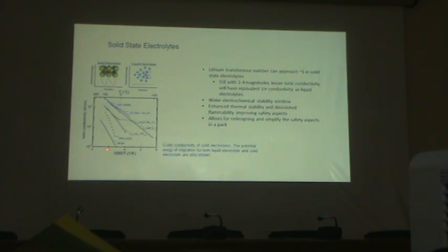So your room temperature will be somewhere around here, 3.1 or 2. At room temperature, already the solid electrolyte is showing conductivity similar to the liquid electrolyte. That is around 10^-3 Siemens per centimeter. So that is already achieved in solid electrolytes. There are other issues, but solid electrolytes can achieve that, certain families.